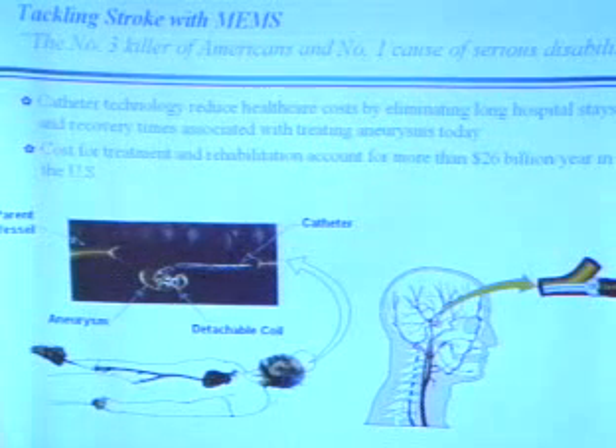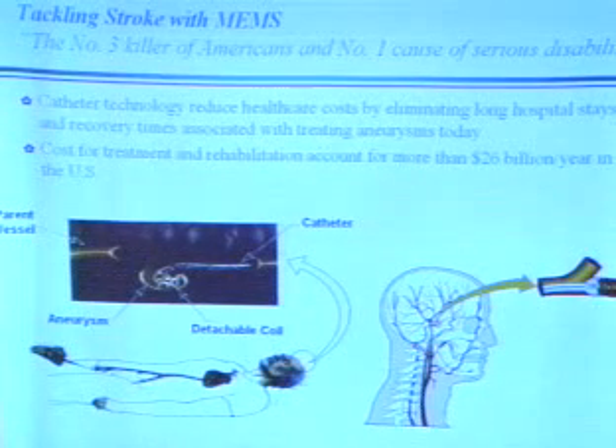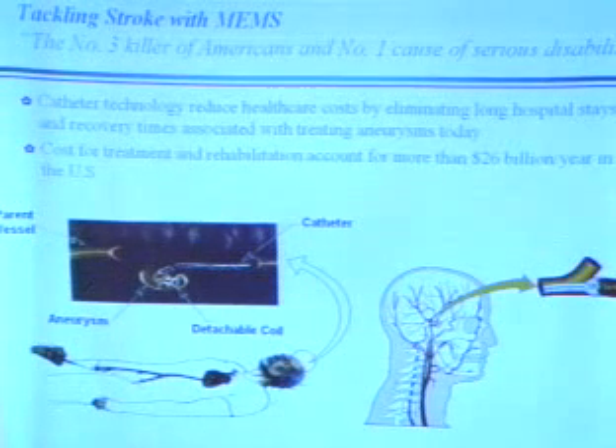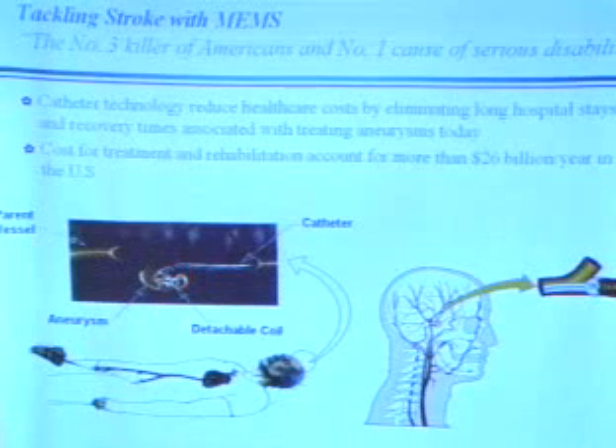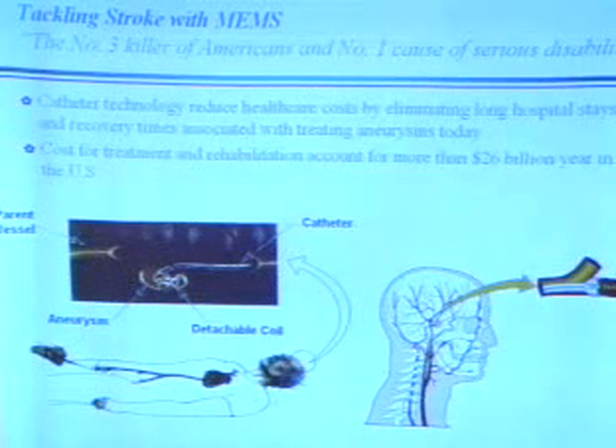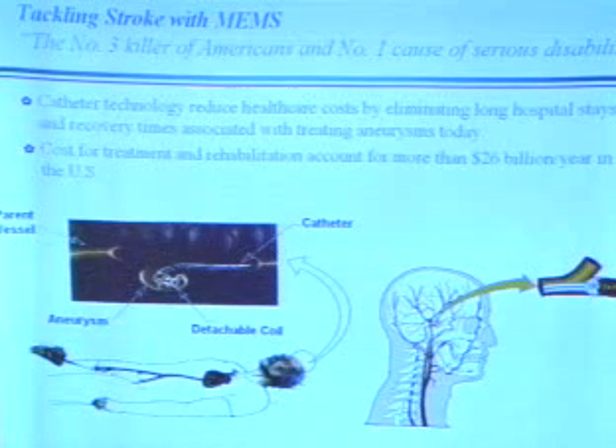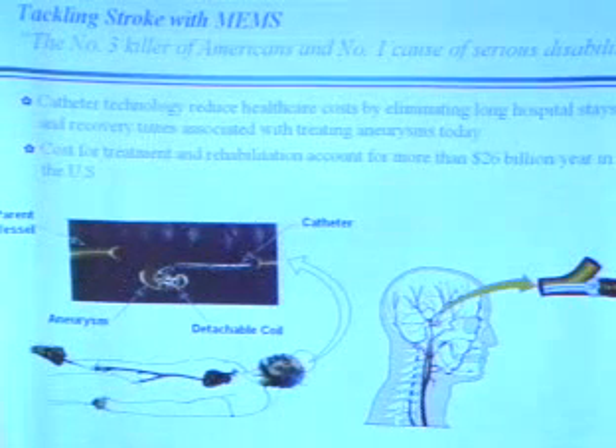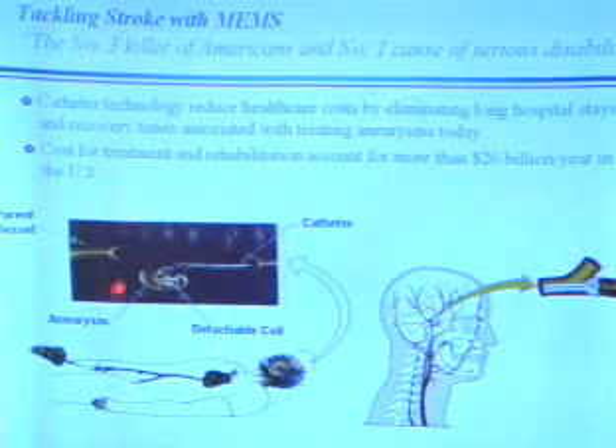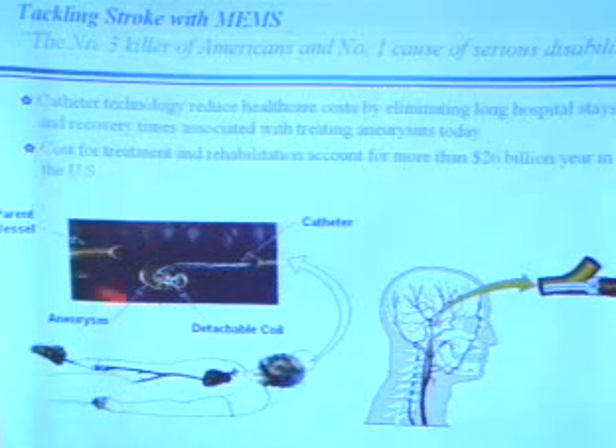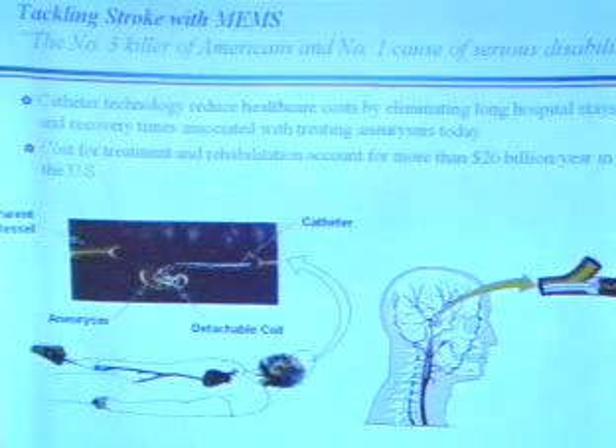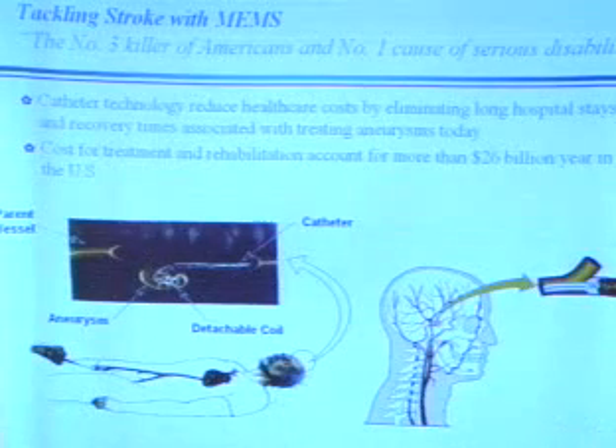There's not much to do about stroke. I mean, it either happens or doesn't, and you just take care of the results and the consequences. But the key to do this is, again, to release this coil. It's one dimensional, of course, a threaded wire, but once it comes into the aneurysm, it starts to coil up again. It becomes a three-dimensional ball-like thing that fills up this chamber. And because it's coated with embolic material, which means blood comes in and coagulates, it eventually closes up this aneurysm neck, and allows blood flow to return to normal, and that will eliminate the ballooning effect.